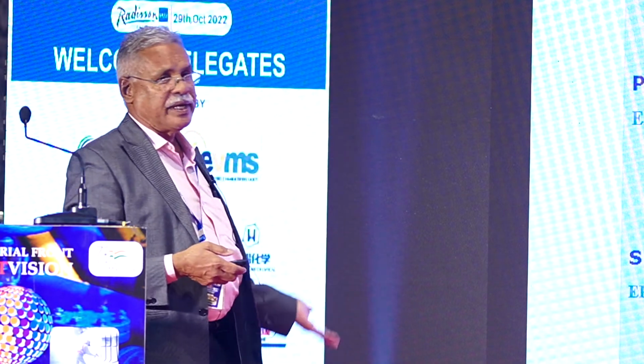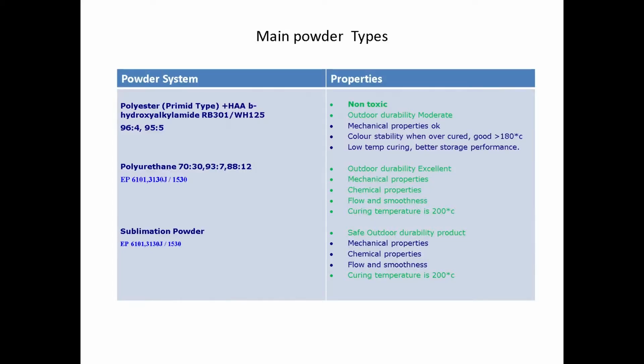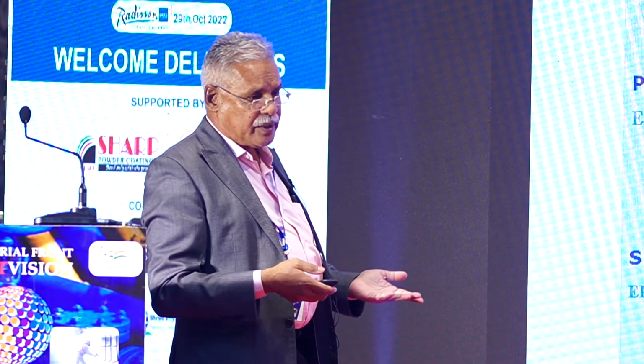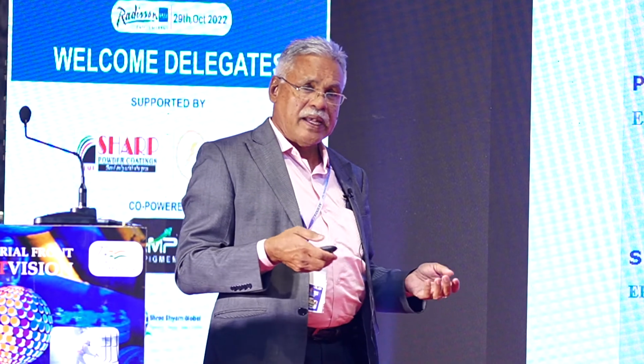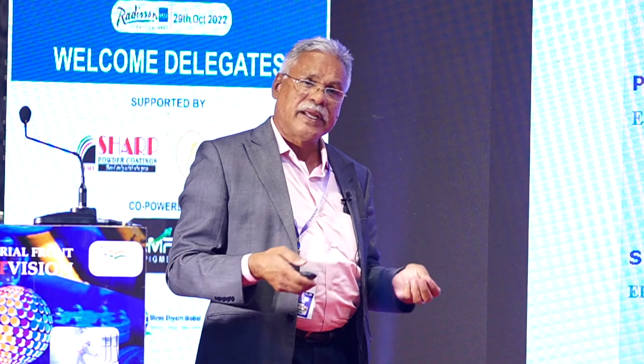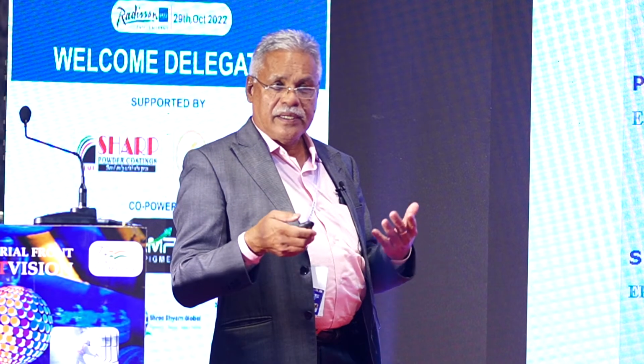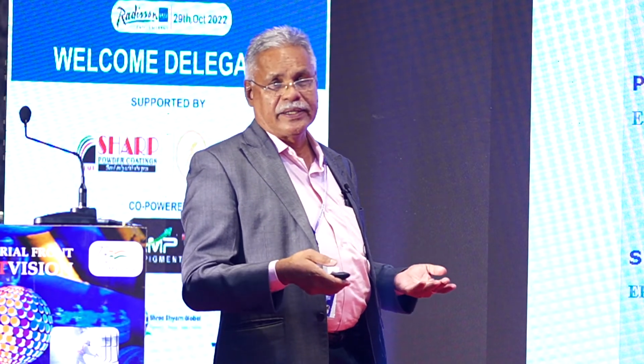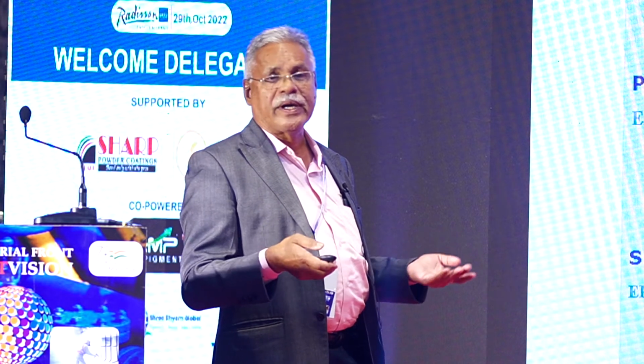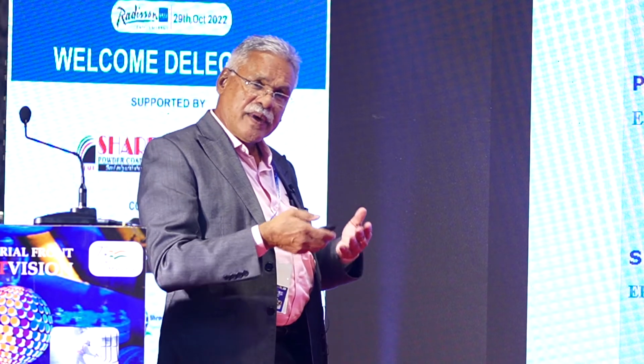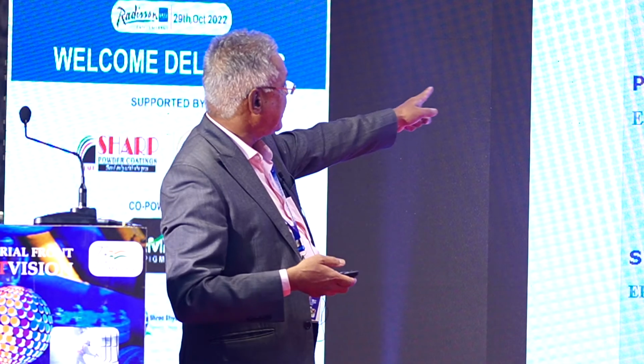Then comes polyurethane. Somebody gave a presentation on a specialty product, in that polyurethane will come, 70-30, 93-7, 88, any combination. It will depend upon the polyester which one you are using and what is the hydroxyl value of that product. So based on that hydroxyl value, you have to cross-link with a suitable hardener, that is blocked isocyanate. Those things you have to cross-link, and based on the OH value, hydroxyl value, and the NCO component, you have to cross-link. So the percentage also they will fix.